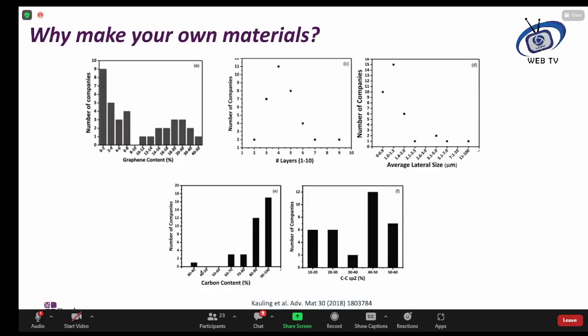And in some cases, you can see that had considerably less than 100% carbon content, and even the best of them only had 50 to 60% of sp2 carbon content, which means that a large fraction of the material could not be described as graphene.